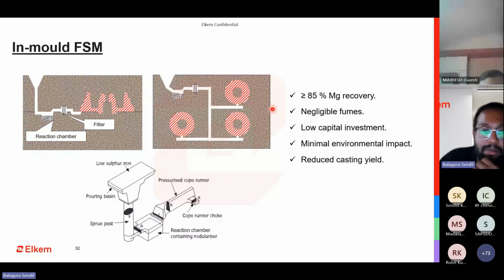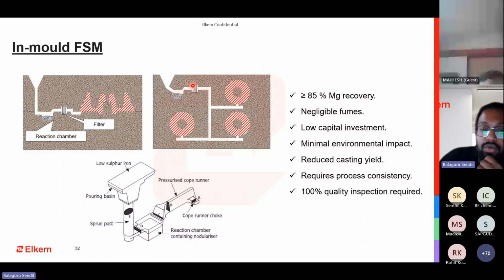The drawbacks here are that it reduces your casting yield. In a particular mold here, if you have a ladle FSM treatment, you can put one more casting here and improve your casting yield. And it requires a lot of process consistency. Your base sulfur needs to be extremely controlled. Your amount of trace element needs to be controlled. And then you need to do 100% quality inspection of all your castings. So these are used for special types of castings, low volume castings, but which need a lot of critical applications. That is where they use in-mold FSM.